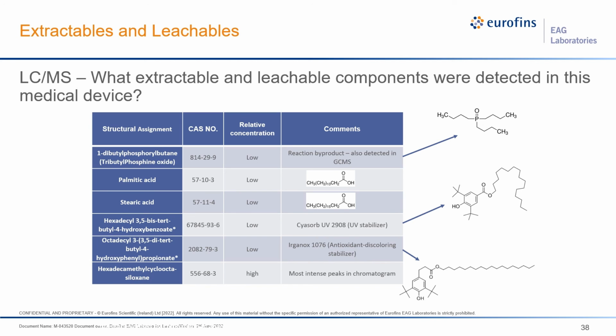We also detected palmitic and stearic acid. So these are fatty acids that are typically found together, and they're common processing aids. We also detected 2 UV stabilizers or antioxidants in the forms of Cyasorb UV2908, as well as Irganox 1076. These were also confirmed to be extracted from the sample through analysis of analytical grade reference standards.